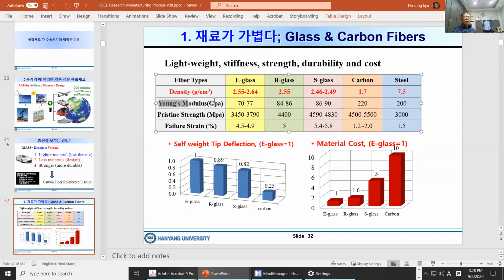Now Young's modulus, this is for the fiber. Young's modulus wise, E-glass is about 70, R-glass is 80 to 85, and S-glass reaches 90, and carbon fiber is like 220 gigapascal. Steel, as a reference, is about 200 gigapascal. These are numbers we need to remember, we need to understand. Again, please memorize all these values.